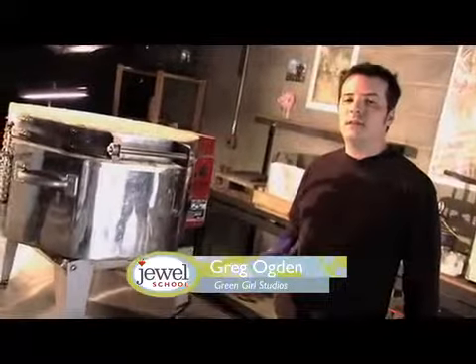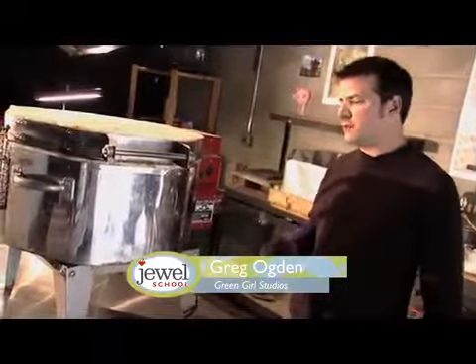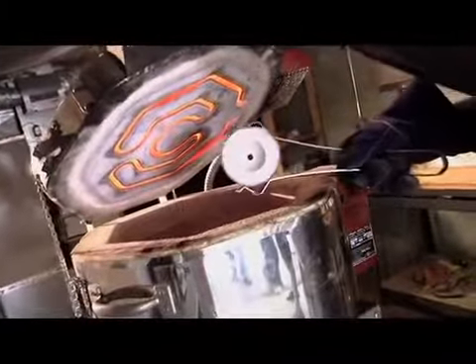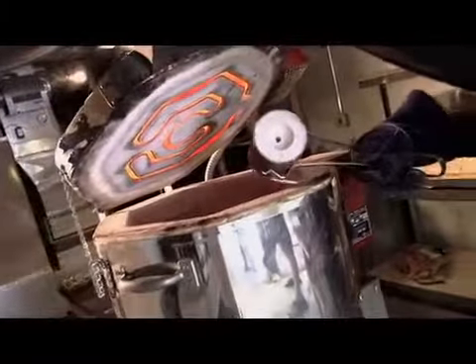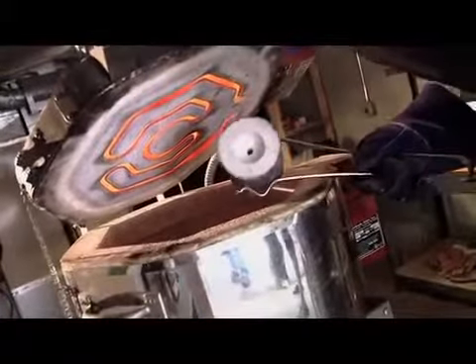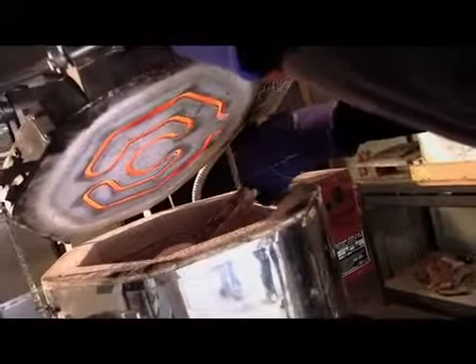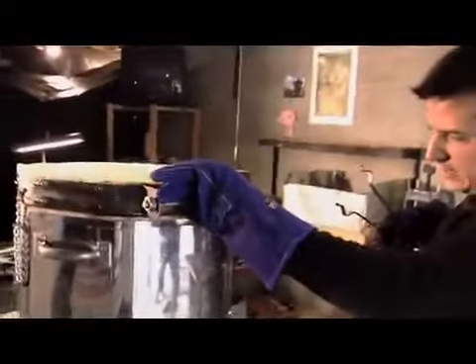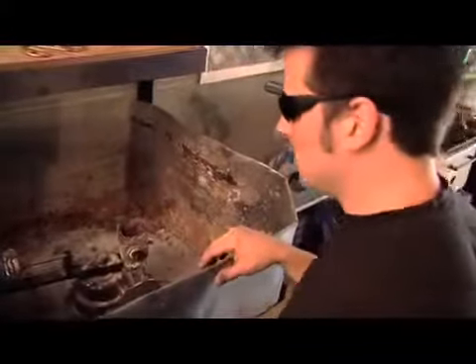So once the flask had set, the plaster had set, we put it inside the kiln and burned it out for about 6 or 7 hours at 1250. Once the burnout's done, we're going to check and see if it's ready to cast. And what we're looking for here on the opening at the bottom of the flask is a nice cherry red interior, which this one appears to have. It's also really nice and white on top, which means all of the carbon has burned away. So it's time to go. We're going to turn it upside down, put it back in face up with the opening of the flask facing the heating element, so it's really hot when the metal enters and has time to make it into the entire mold. All right, so the flask is in the kiln and it's ready to go.